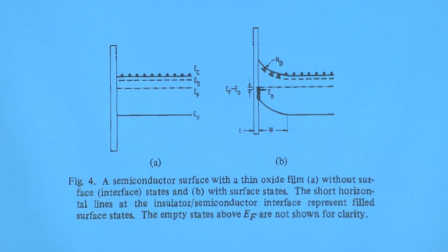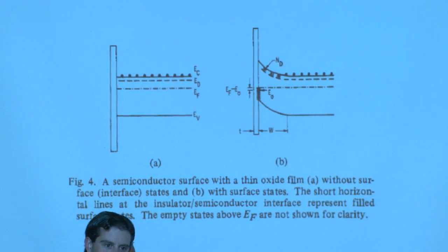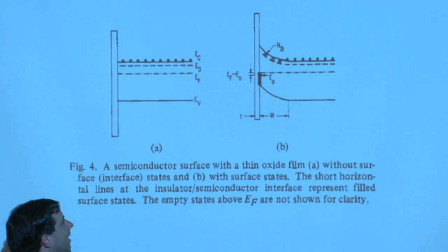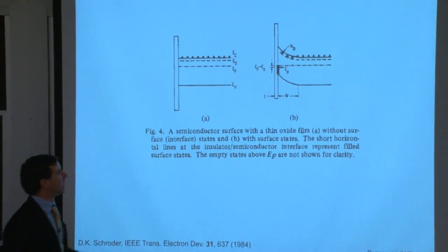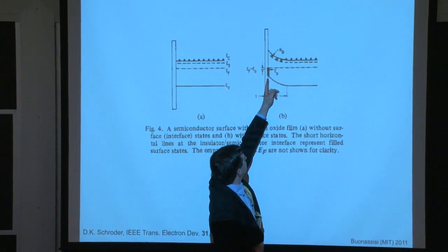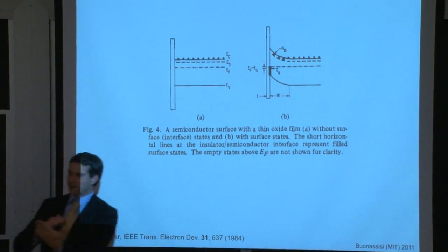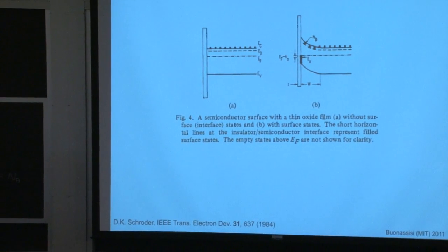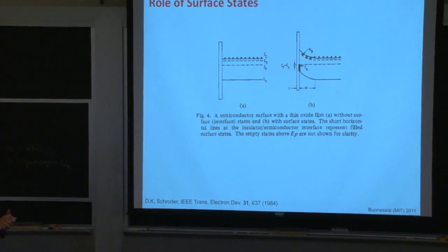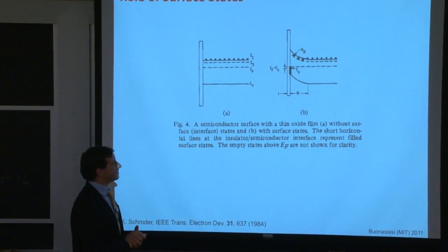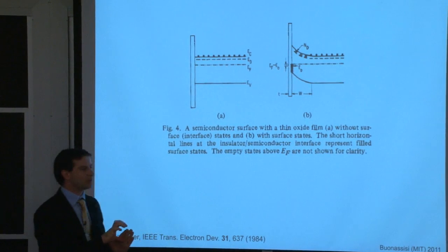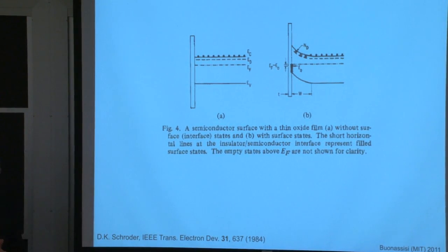So as you begin filling in those states, another way to think about it is that you're pulling the Fermi energy toward mid-gap, because now as the electrons are depleted from that near-surface region, as they fall into those mid-gap surface states, the Fermi energy is going to shift towards mid-gap. And if you indeed look at the semiconductor right here at the surface, you'll see the Fermi energy is almost at the mid-gap. And so this is a very curious phenomenon that occurs in many semiconductors. There's a natural band bending toward the surface depending on the surface chemistry.